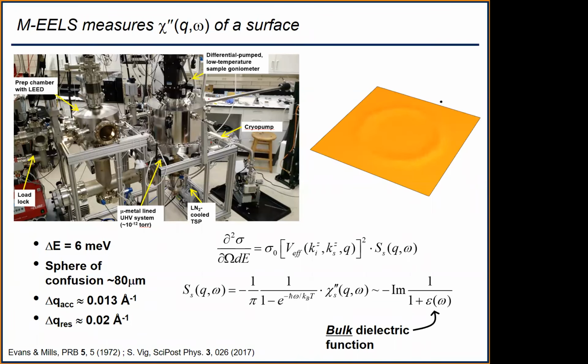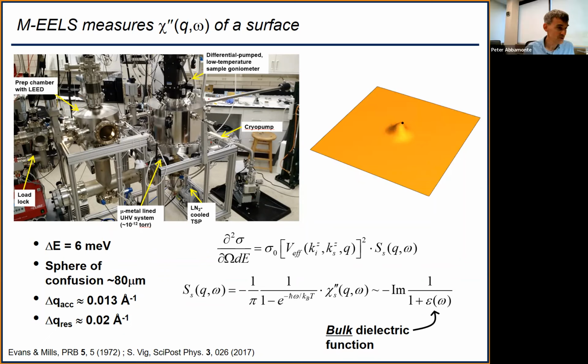But I thought strontium ruthenate has surface reconstruction, right? Does that affect it? Yes, I have a whole set of slides on that. I was assuming no one would know. There are two reconstructions. There's a structural one where the octahedra rotate. And then there's a surface state band that comes when you break the ruthenium-apical oxygen bonds. And that could itself have a plasmon, a 2D plasmon. So we actually got rid of that.